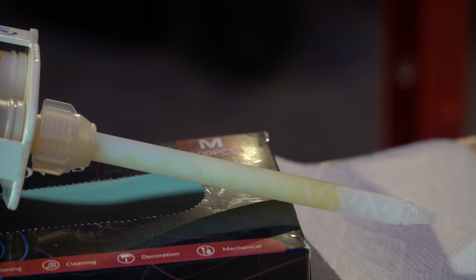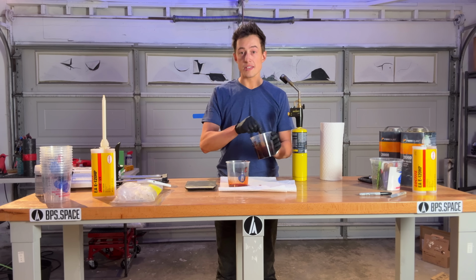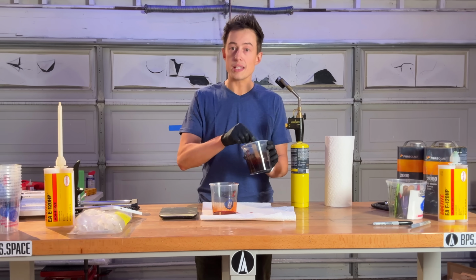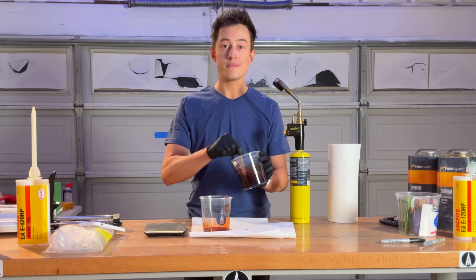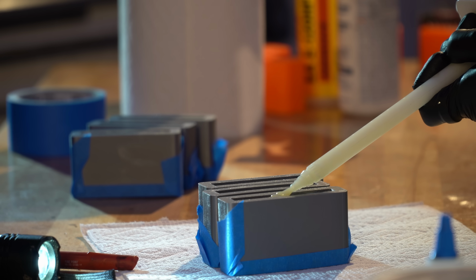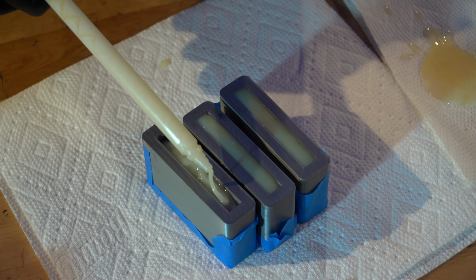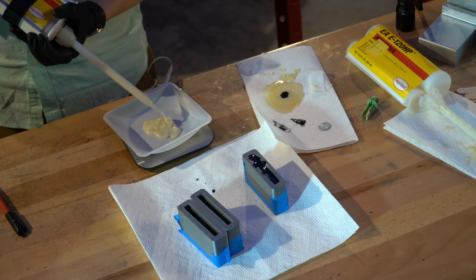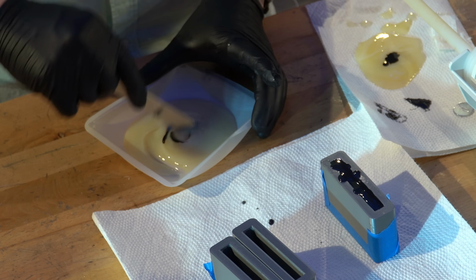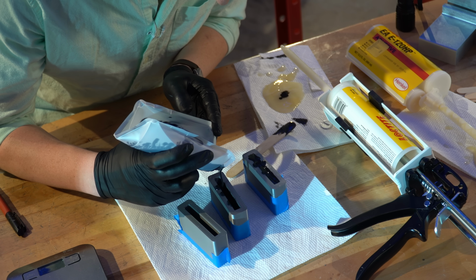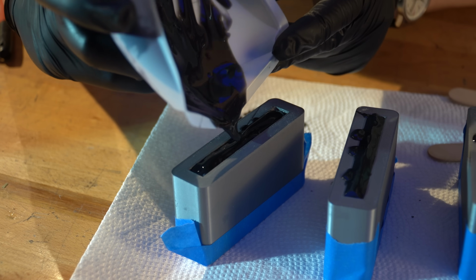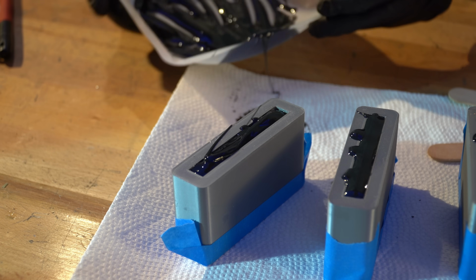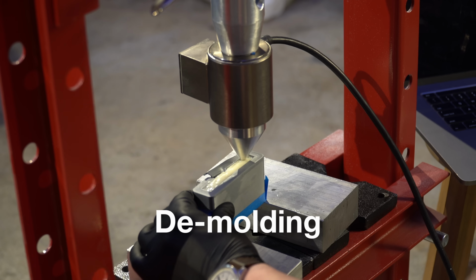I'm not convinced though. Intuitively, it seems like hand mixing would be more thorough. So let's put it to the test. Let's run the experiment. I'll make 3 test coupons in 3D printed molds, then fill them with epoxy. One batch is epoxy right out of the mix nozzle, and the other batch uses a mix nozzle with extra hand mixing and a little black dye to differentiate them. Although, won't the black dye skew our results? Hold on to that thought for a minute.